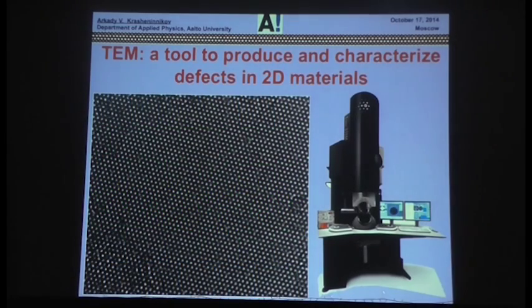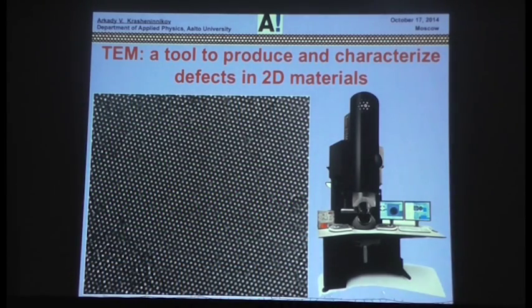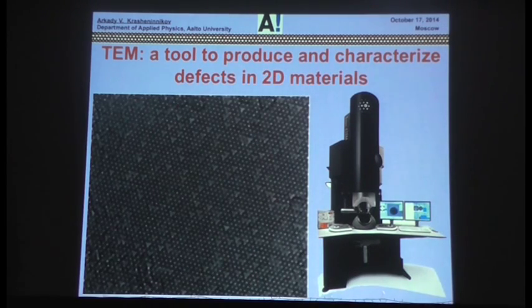For example, this is a molybdenum disulfide sample, which looks pretty nice, but immediately the trained eye of a microscopist like Dmitry may notice some defects. If you process the image, you filter out some noise. With exactly the same image, you use some software tricks to make vacancies more visible. You see that there are actually quite a few vacancies in the sample, these triangles. These are vacancies. And the question is, where do the vacancies come from? Are these native defects which exist in your sample before you put it into the TEM chamber, or are these artificially created defects by the electron beam?